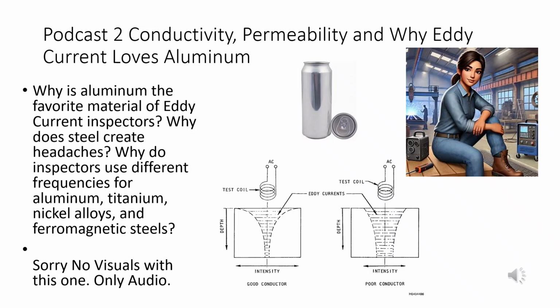Conductivity in welding engineering. This is where your welding background becomes useful. Think about precipitation hardening. Suppose we take 6061, solution treat it, then we age it. What happens? Strength changes, hardness changes, microstructure changes, conductivity changes too. The same metallurgical events that affect strength affect conductivity. That is one reason ET can sometimes be used to verify heat treatment condition.